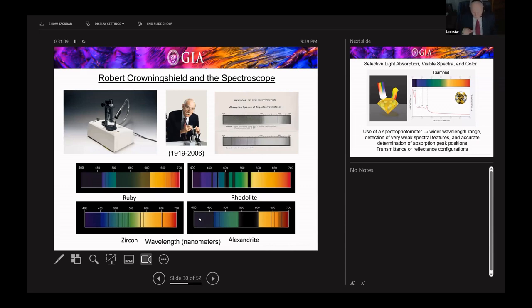And I just show you a couple of examples at the bottom, a couple of colored stones, ruby, zircon, and so on. You see the color spectrum, you see 400 to 700 nanometers, and you see a pattern of dark bands. The dark bands are the regions of the spectrum that the gemstone is absorbing. So you have white light coming through, and part of that spectrum is absorbed. You're going to see sharp bands or broad bands. And of course, because you have the wavelength scale, you can get a pretty good idea where the bands are located, the nanometer positions.